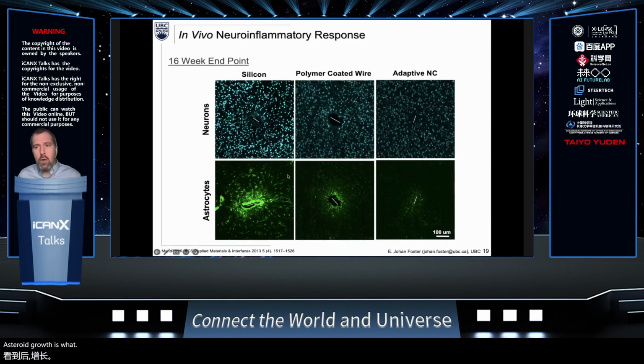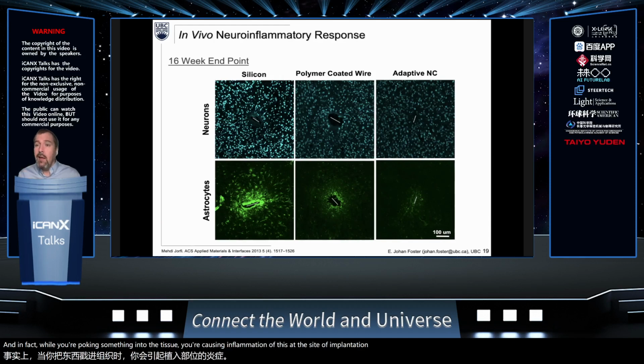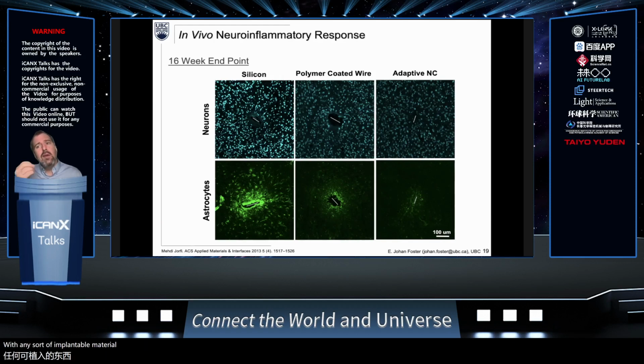Astrocyte growth is what you don't want to see. That's essentially the defense mechanisms at work. And so in the case of the silicone and the polymer-coated wire, you see significant astrocyte growth. In the adaptive nanocomposite, you do see astrocyte growth. It's not a perfect material. And in fact, while you're poking something into the tissue, you're causing inflammation at the site of implantation. And you will always do that with any sort of implantable material. So want to be aware.